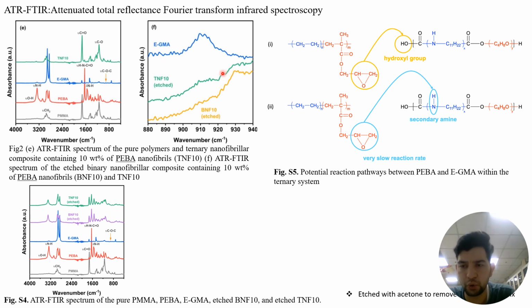Figure 2F and S4 show the ATR and FTIR spectrum of each sample. Here we etch PMMA with acetone. Looking at the graph, this sample is in the presence of EGMA and this one is without EGMA. So the author did the FTIR spectrum.